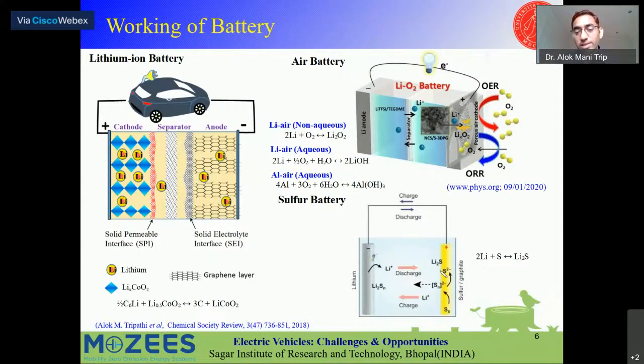And this electrolyte allows the lithium sulfur battery. So one interesting thing I'd like to tell you: when the lithium ion battery was first discovered, it was again a sulfur based chemistry, because the cathode was titanium sulfide, but because of the low potential it was discarded, and then the cobalt based system came, and finally this became the champion in the battery market. So with the sulfur battery, the lithium reacts with the sulfur, forming Li2S. But the problem with this battery is that lots of other polysulfides are forming, which is a drawback. Lots of things are coming in research, which is improving the performance of these batteries.